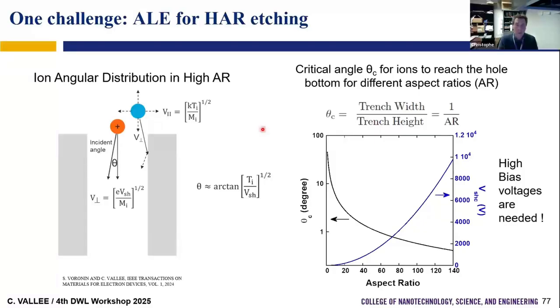Another challenge we have for high aspect ratio etching is the control of the ion energy. What is important to understand is that when we do high aspect ratio etching, we want to have energetic ions coming to the bottom because we need to do the etching at the bottom. But the ions come perpendicular to the substrate thanks to the bias, but they also have some lateral velocity because they have some energy. And so depending on the ratio between the two velocities, they don't have a perfect angle of 90 degrees. So you have some dispersion, what we call ion angular dispersion.